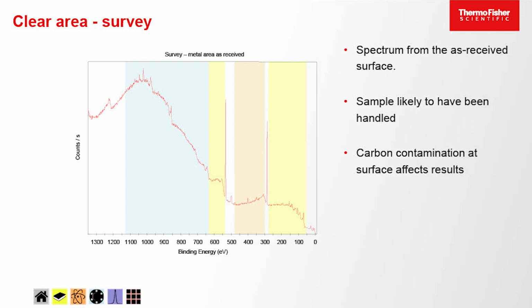Remember, binding energy 0 to 1350 here, but kinetic energy, what we're actually measuring in the instrument, is 0 over here and the maximum over here. So the more we are over in this direction, the more slowly those photoelectrons are traveling. And if they're losing energy, then we'll start to see more of them here. So this curving down, carbon at the surface, this curving up, this will be the oxide on the surface of that metal, and that's underneath the carbon overlayer.